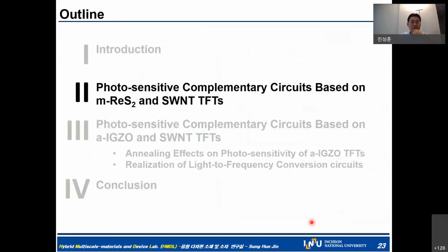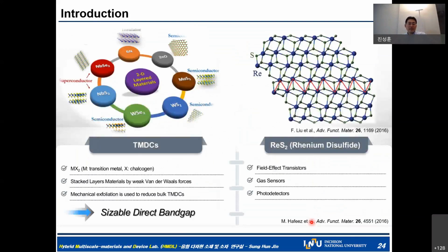The photosensitive complementary circuits are based on the multilayer rhenium disulfide and carbon nanotube transistor that we recently introduced. Typically, there are many kinds of transition metal dichalcogenides. However, rhenium disulfide has a very interesting property: its band gap is not much affected by the number of layers, as compared with other transition metal dichalcogenides. Moreover, it has very high mobility as well as good electrical properties in conjunction with photodetectivity. Those materials can be implemented toward complementary circuits, particularly by using the p-type property.